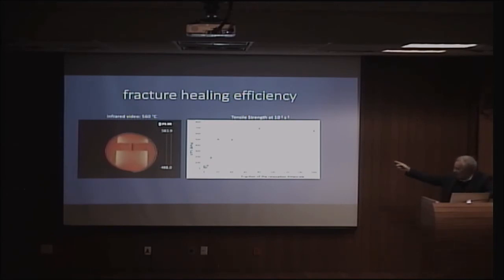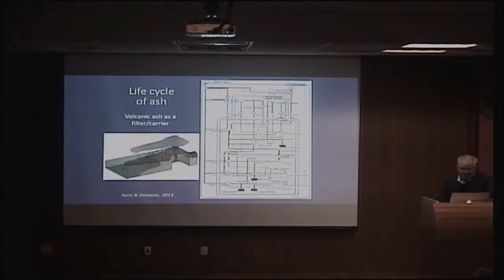And what we're measuring is the stress that is required. This is Jan Lavallee's work. We're measuring the stress that's required to pull them apart. And you get a fundamental relaxation time before it's completely sealed together, before you get something like a tuffisite, where you know it's broken from looking at a tuffisite, but if you crack it, you'll get a conchoidal fracture which runs clean across it. No heterogeneity of properties.